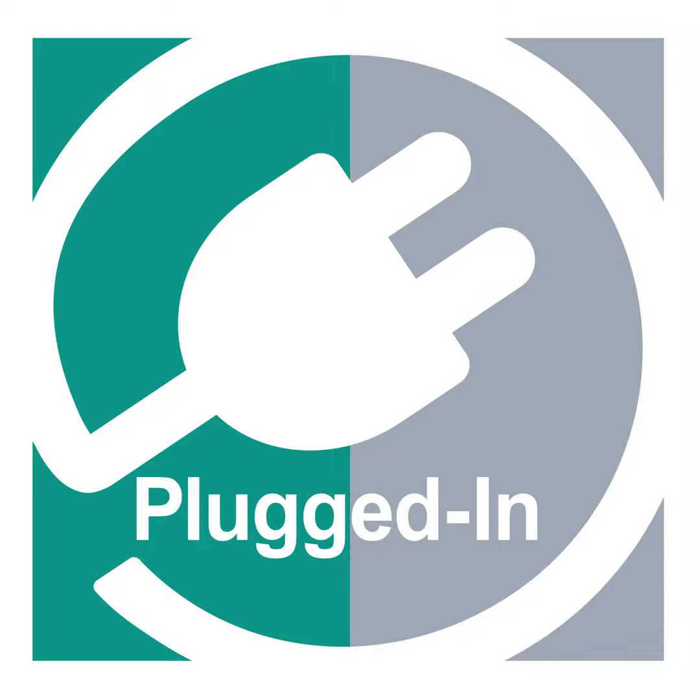Right. So irradiation is effectively the practice of applying ionizing radiation to a polymer to cross-link it. And cross-linking is joining polymer chains with ionic or covalent bonds. And what this does is give them better mechanical and thermal properties. And at PNF, we're phasing out some of the irradiated materials that we used. Why is that? There's environmental and health risks, and it's also more expensive to do. When we can replace those materials with more application-specific ones like POC. I see. Okay, good. That's right.